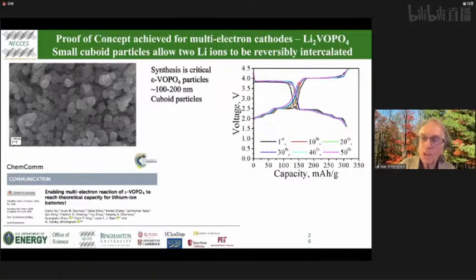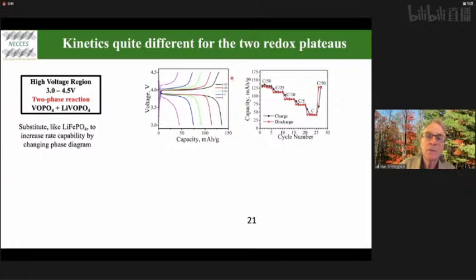All is not over with, there was still a number of challenges. If we look at the kinetics for these 2 reactions, they're very, very different for the high voltage plateau and the low voltage plateau. So in the high voltage plateau, it's a two-phase reaction, VOPO4 to LiVOPO4. And you can see as we increase the rate, the black one is the slowest rate, we're losing capacity. And we plot it again on the right-hand side the same way. So at a 50-hour rate, we get about 130 to 140 milliamp hours per gram. When we go to the C rate, that's 1 hour rate, we're down to about 30 or 35.